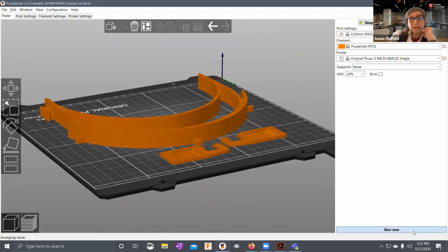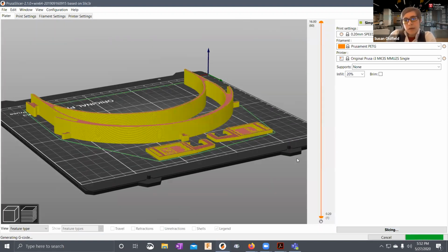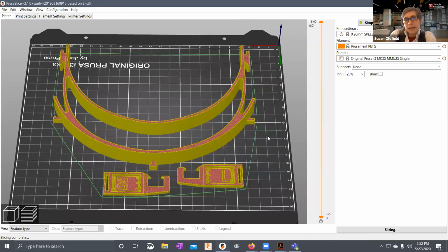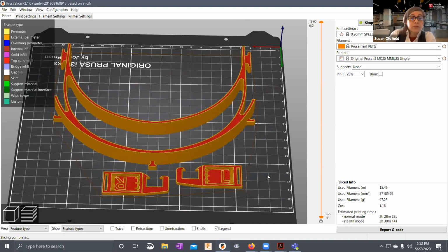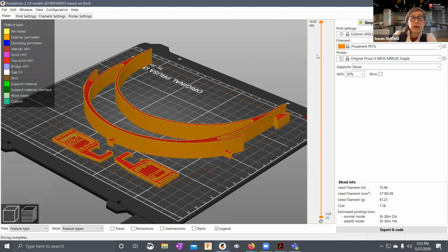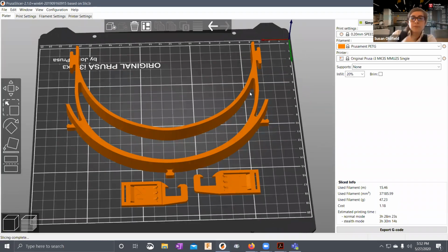In fact, let's click slice now. It will take 3.5 hours to do this at a 0.2 layer height. I had tried making shields with a higher layer height, but another reason to go for a larger nozzle is that with a 0.4 nozzle, you can't really print larger than 0.2 and get good results. If I print with a 0.3 layer height, I get something like a wicker basket, and that's not going to cut it.